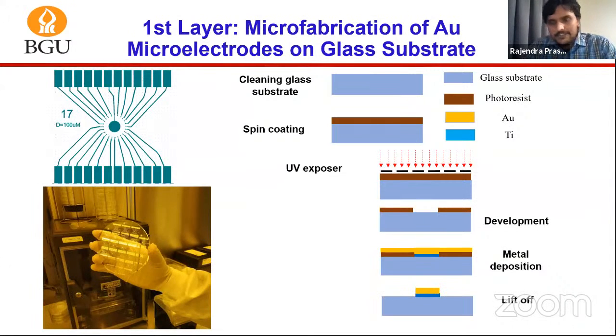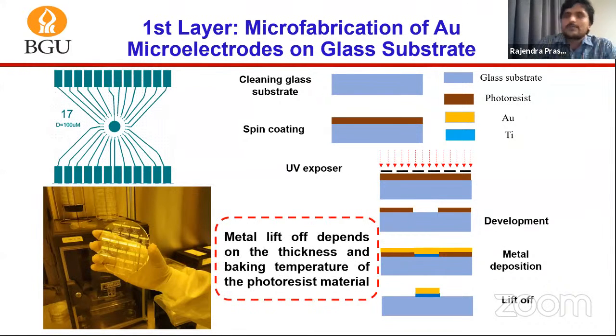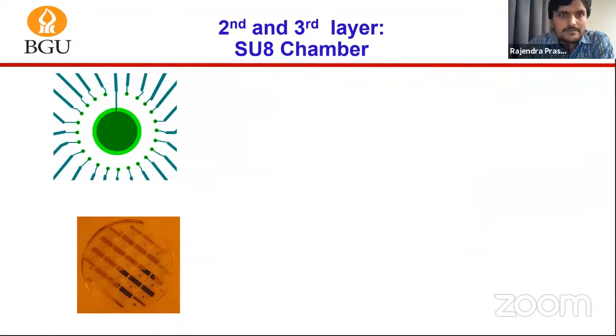And after the lift off process, we achieved the microelectrode array chip on the glass substrate that you can see here in the picture. During this process, there were various parameters to optimize, and we did it very nicely, and we achieved 100% yield for this microelectrode array chip microfabrication.